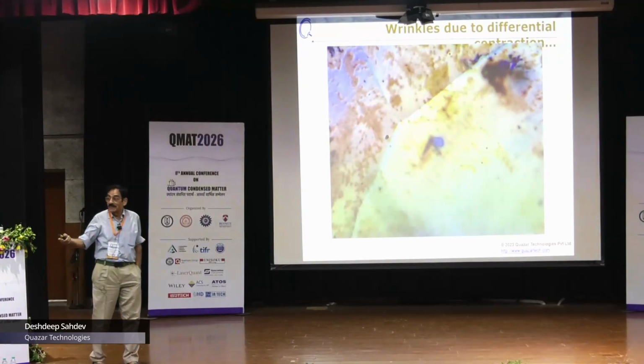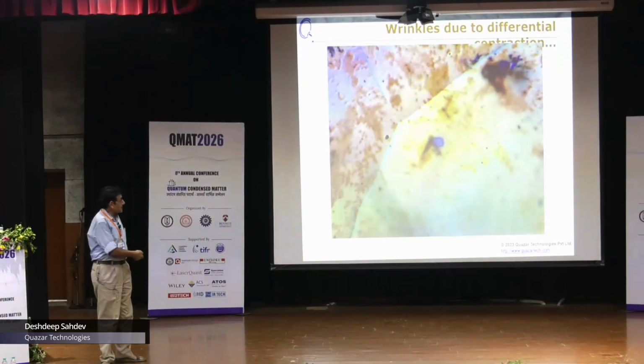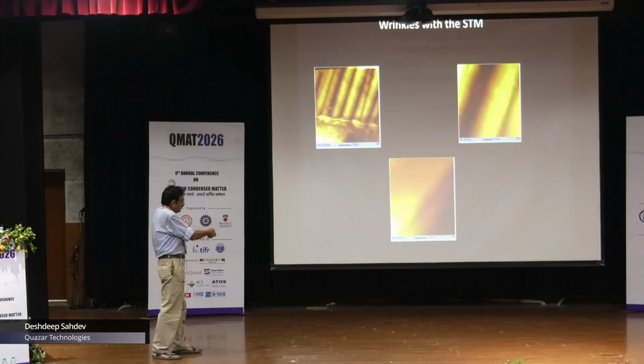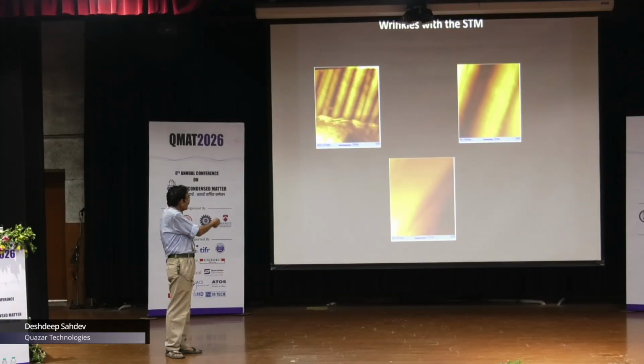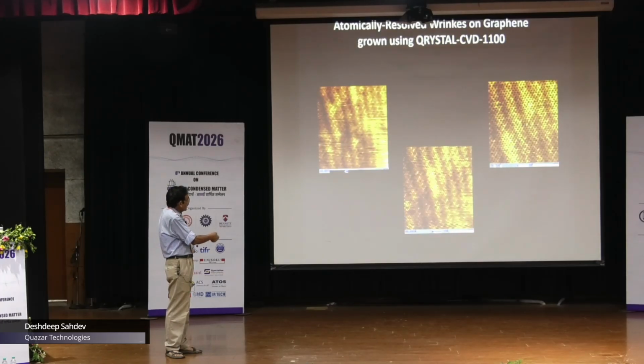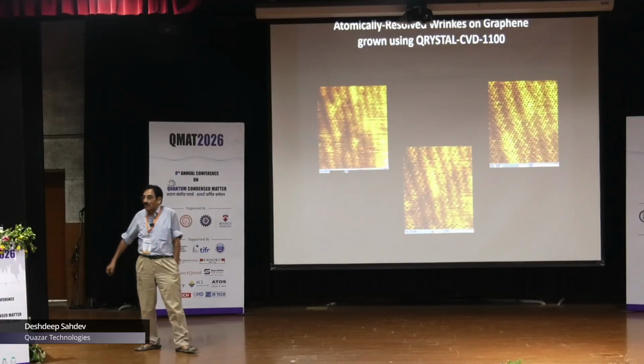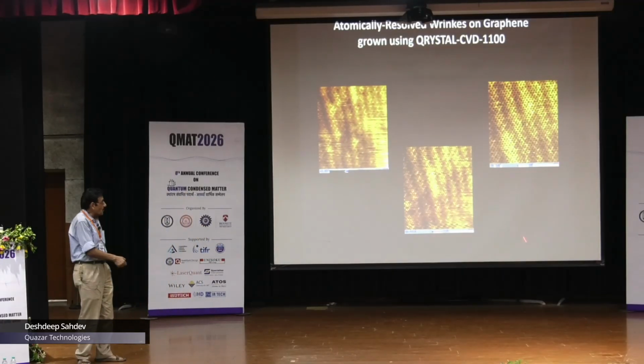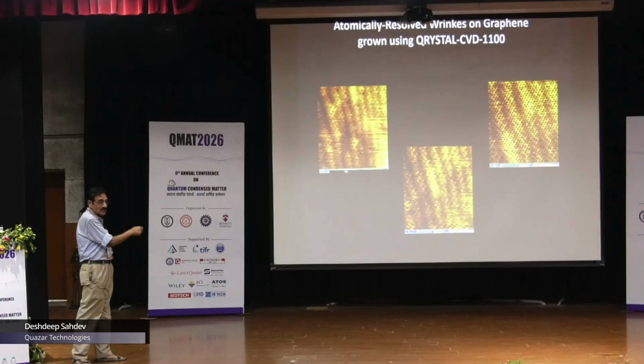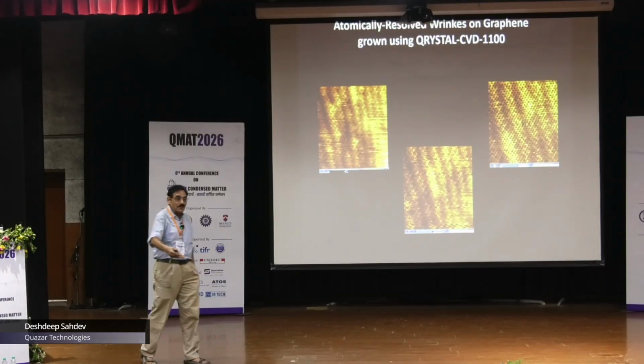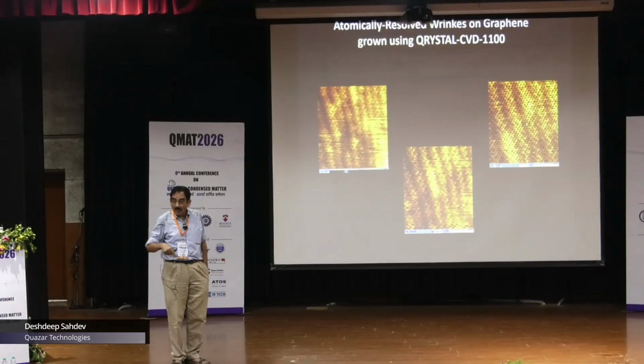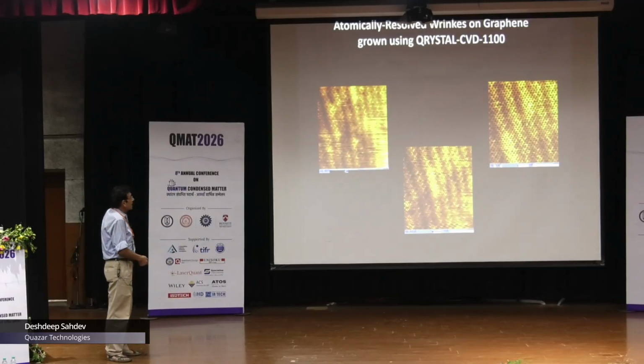But then we have an STM with which we can see it much better. So we looked at it under the STM, we start seeing the wrinkles much better, but we go one step further, and lo and behold, you not only see the wrinkles, but you resolve the atoms. You see the whole hexagonal benzene rings of atoms. These are beautiful images that you see of the wrinkles with the atoms fully resolved on the wrinkles, all right? So this is stuff that we did with our STM.